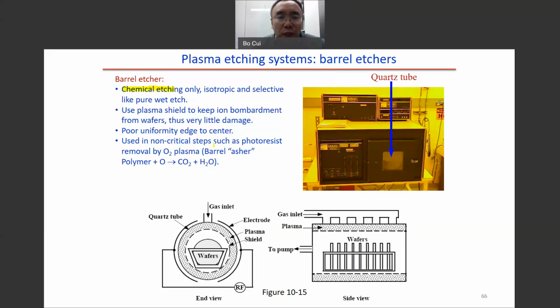This is not used for the critical etching. It's only used, for example, to remove the photoresist residue. You just want to remove the material residue. You don't care about the etching rate. Then you can use the Barrel Etcher. To remove the photoresist, we use oxygen plasma. This one is chemical etching, very selective, but it is not anisotropic. It is isotropic etching.